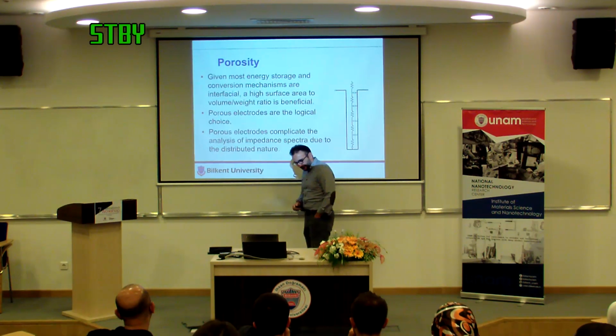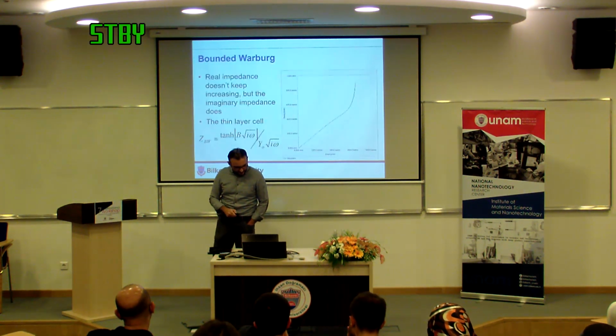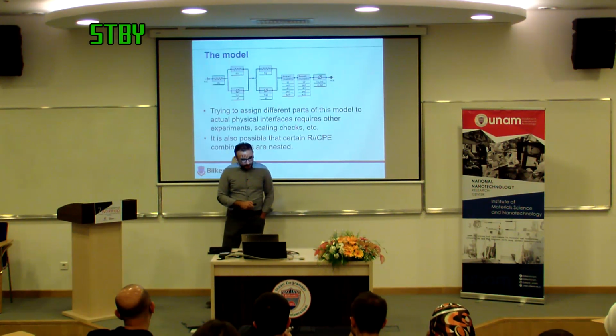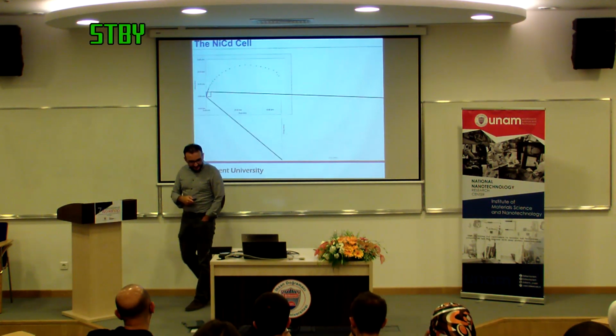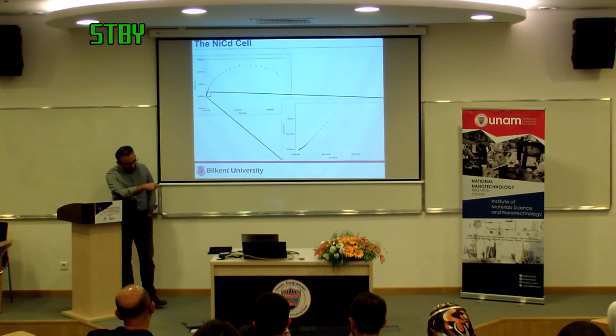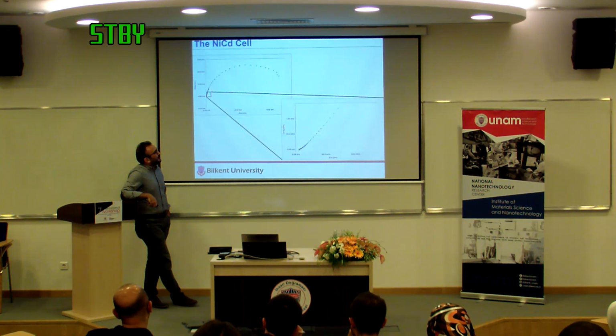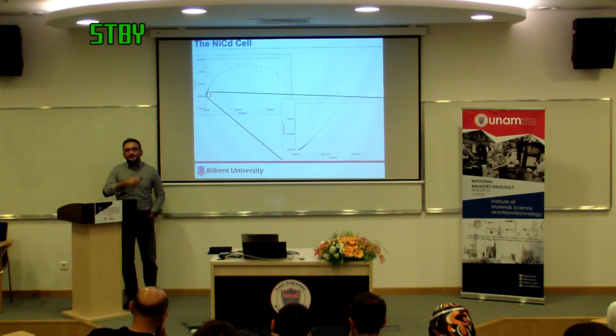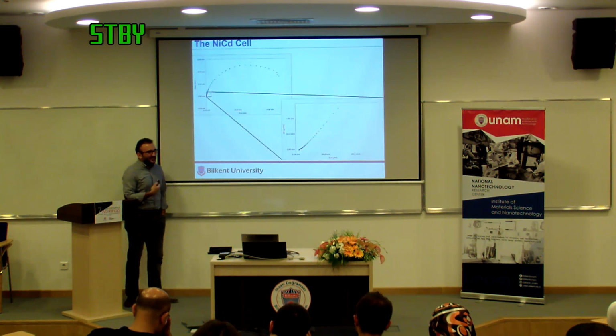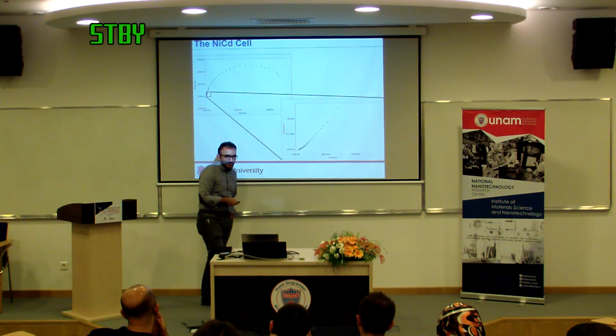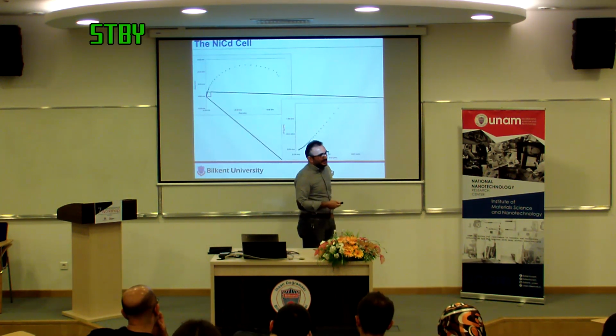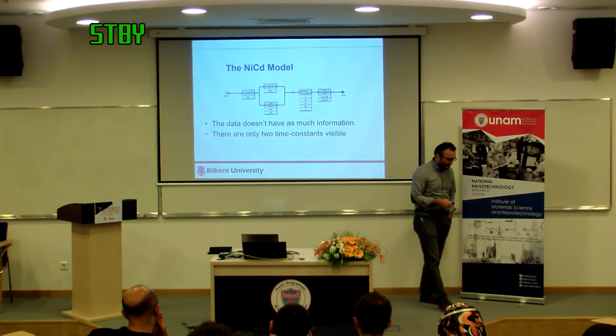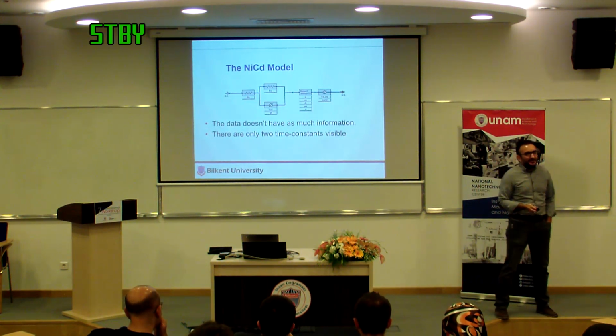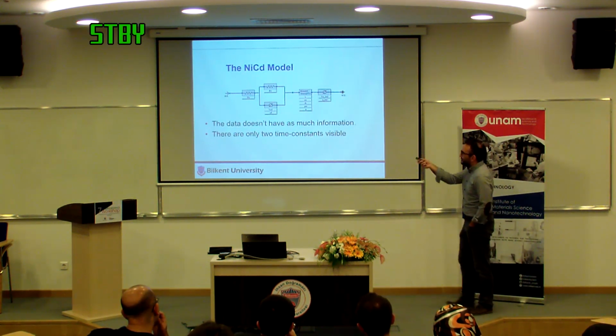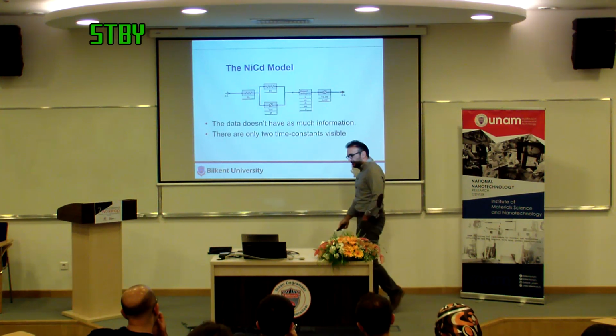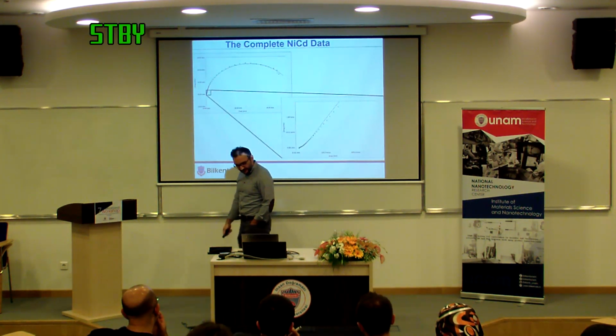So let me go back to where I was. All right. Now I fit the lithium-ion cell. Let's go back and try to fit the nickel-cadmium cell. Now I could have used the exact same model to fit the nickel-cadmium cell, but the nickel-cadmium data does not have that many kinks or bumps. It has much less information. So I fit it with a much smaller model, and the reason I fit it with a much smaller model is because I do not want multi-valued numbers. So this is the smallest model that could fit that data. And here's what the fit looks like.